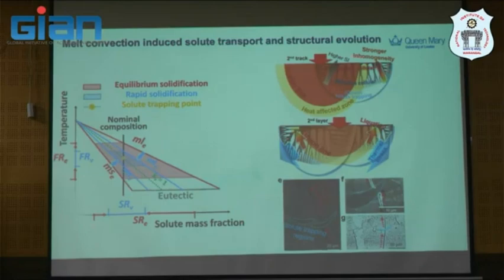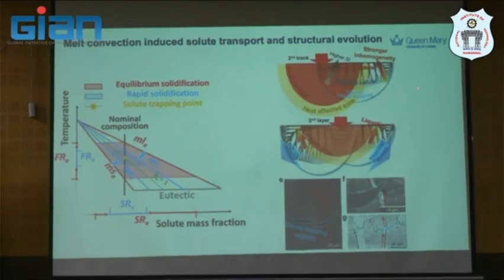And then you will see the strong inhomogeneity of the process here lead to what we call quasi-solute trapping. So when you get strong inhomogeneity here, in the second layer, that will trap a zone like this. I think if you go back to your sample, I bet that you will see this kind of thing as well. Most of the time, that's what we'll observe across the sample. It's not speculation, but I think there's something to do with the process. So that's why we try to relate now.